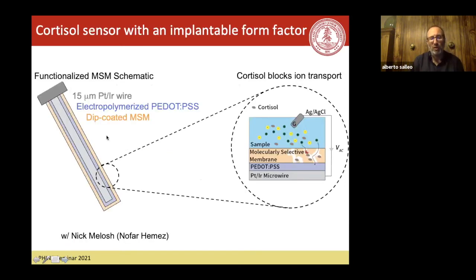This is very simple. So this is work done by Nick Melosh. We collaborated by making the molecularly selective membranes. So they have these 15 micron platinum iridium wires, and then they electropolymerize the polymer, the PEDOT:PSS, rather than depositing it by spin coating like we do. They put the electrode in a solution that has the monomer, and then you pass a current and this polymerizes on the electrode.